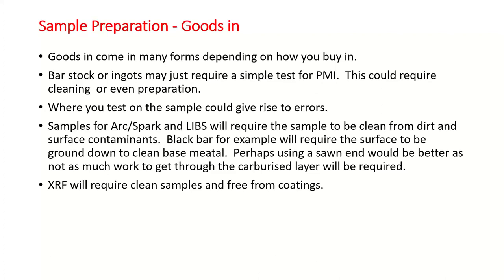Any of these techniques are all surface techniques, so they're actually measuring the surface of the material, even though, in some cases, creating a plasma on there, like the ArcSpark and the LIBS. It's actually burning part of the material up. Anything that's on the surface will be taken into that plasma, so you will be measuring it. So if there's oils on there, you will pick up the elements that are in the oil. If there's a coating on it, then you'll pick that up. If there's like a paint or something like that, then obviously if you've not seen it, you've not cleaned it off. They all contain elements which will then give you a strange result.